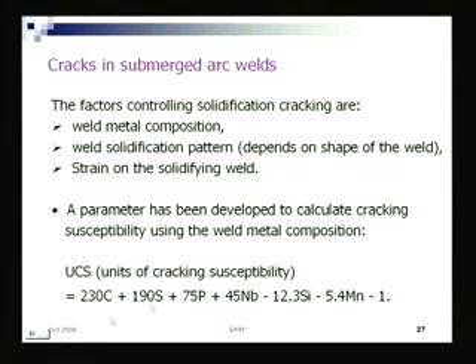What does difficult to weld mean? It means when you weld, it cracks. There is a difference, why? Because of this carbon, as well as sulfur and phosphorus, as you can see, these are parameters which contribute heavily towards cracking susceptibility. That is why a shipbuilding quality weldable steel should have these, sulfur and phosphorus, as low as possible. General requirement is it should be less than 0.05%.